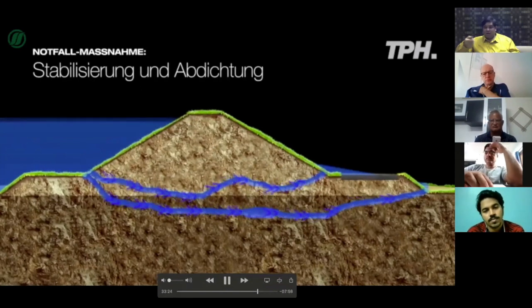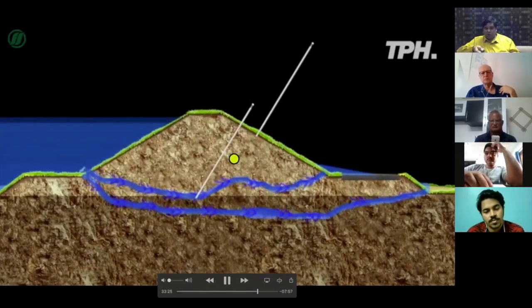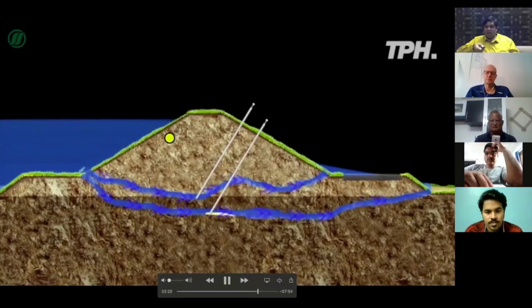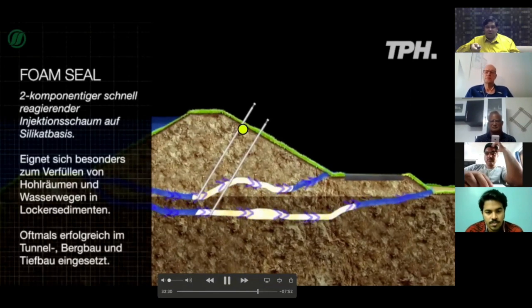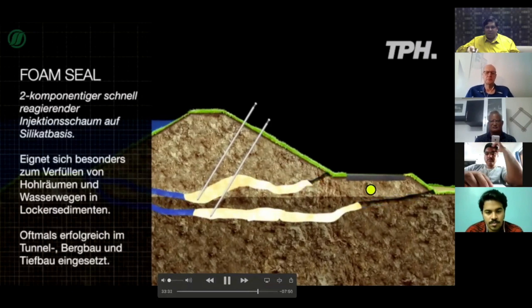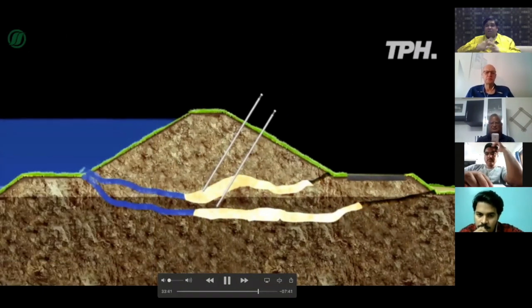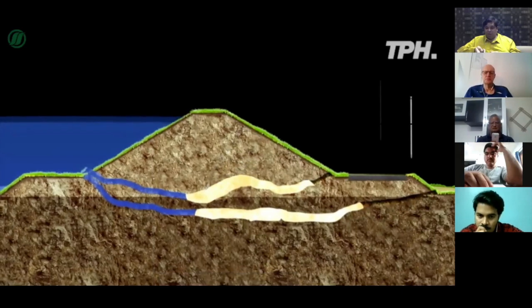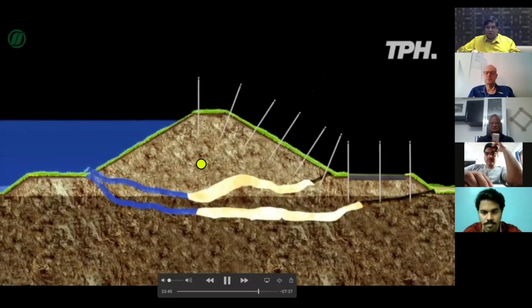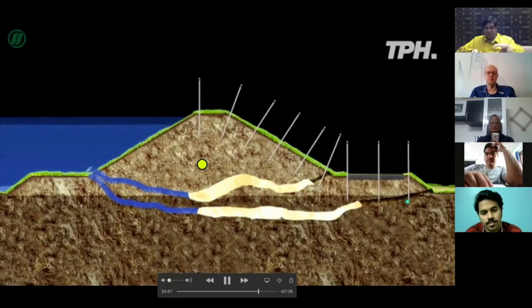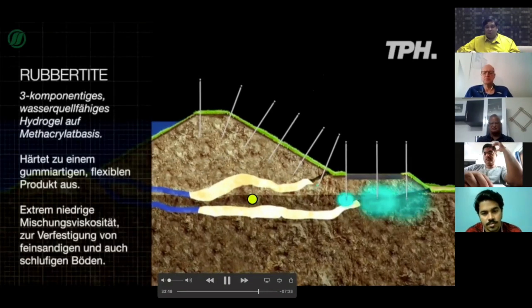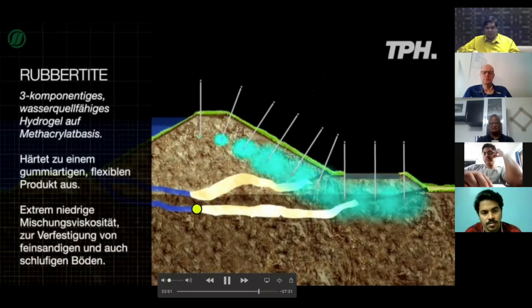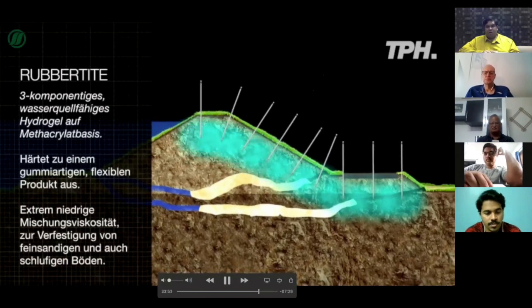So what we need in this kind of case is to stop the water in the first place, and then also stabilize the entire dike system. To stop the water, maybe something like foam seal would be used. It's a two-component, very fast foaming silicate foam. We inject a small area of it, it expands and fills up all the voids that the water channel had created.